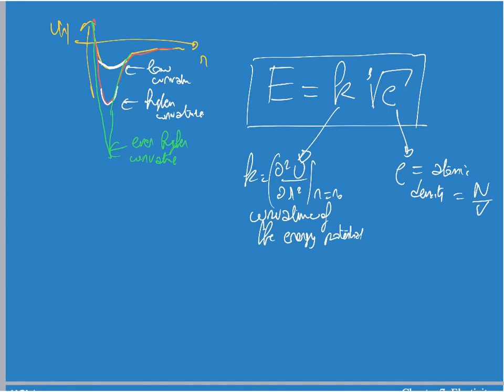Typically you see here that if you have atoms that have the same distance R naught with each other, it means that the position of the minimum is not going to change. You also know that the shape of the function is not going to change. The shape of the energy as a function of distance is always the same. Whatever you do, the energy should go to plus infinity when the distance becomes very small, and the energy should go to 0 when the distance becomes infinite. So this shows you that the curvature is very linked to the value of the energy at the minimum, the position at which you have a minimum of energy. If you have a low U naught, that is to say, if the value of the energy at the distance for which the energy is minimum corresponds to a low value of energy, then it means that you will have a low curvature.